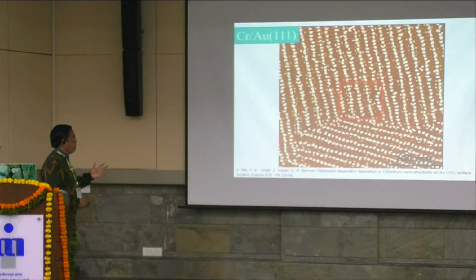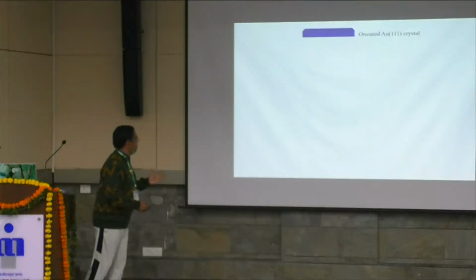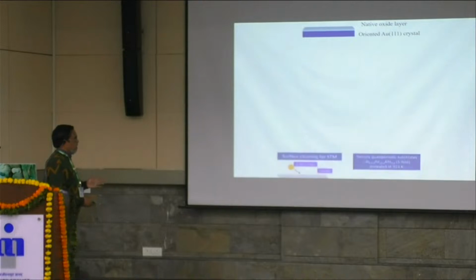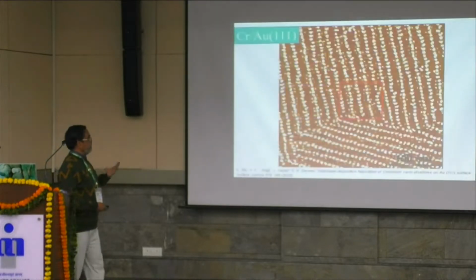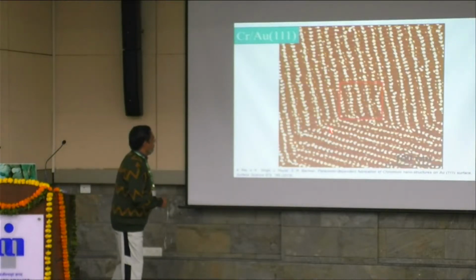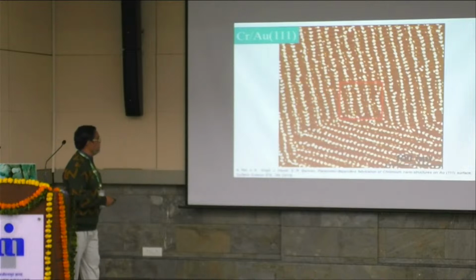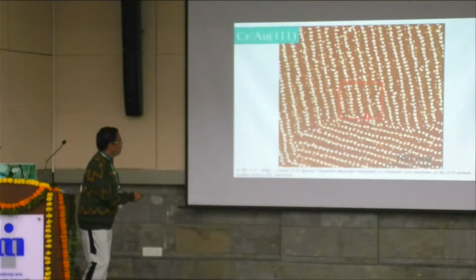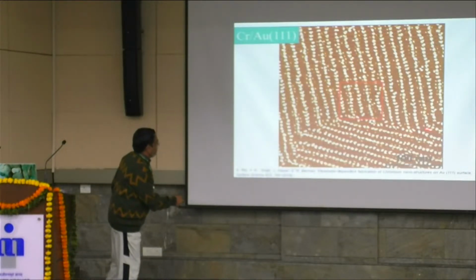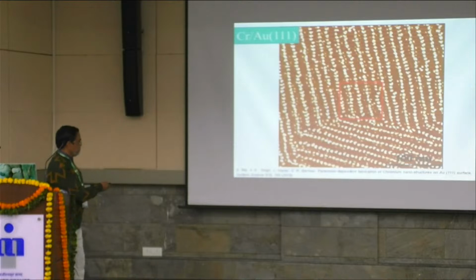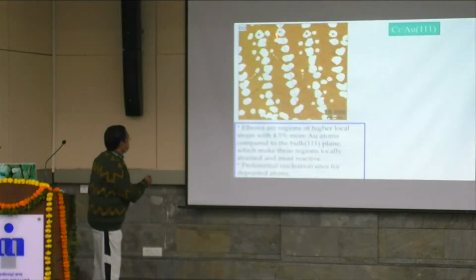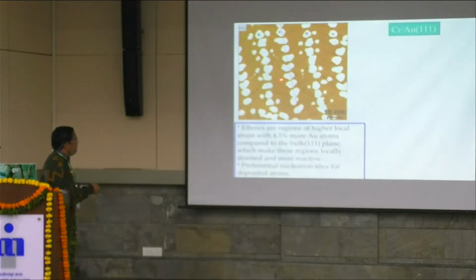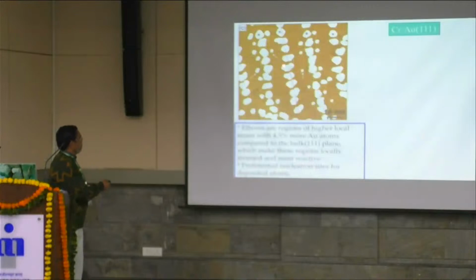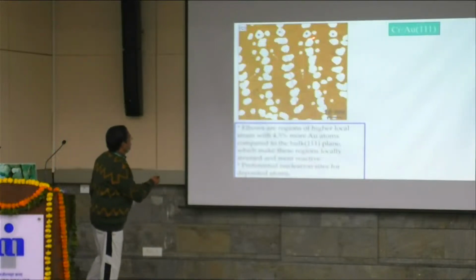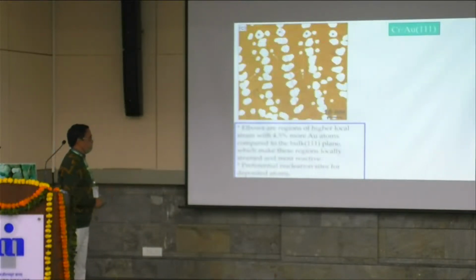Unfortunately, in this one it is not there. Probably in the previous ones it was there, but it will come in a moment. The white means this is high, and the brown means this is low. You can see the gold wiggles, herringbones, below, and these are the chromium islands. If I zoom into the red thing, you can see that these are the chromium islands sitting at the bulged elbows of the gold. These are the bulged elbows. It is sitting at these bulged elbows.